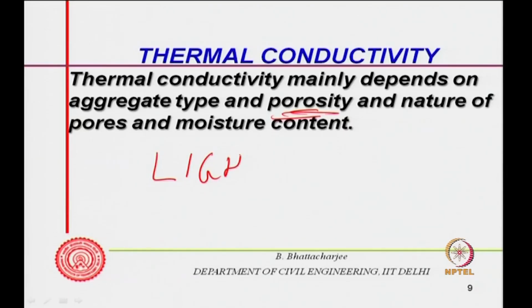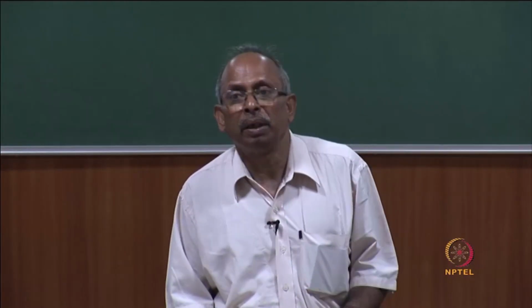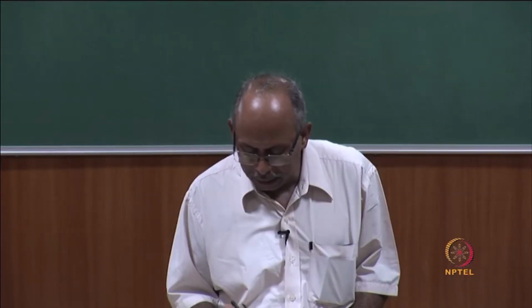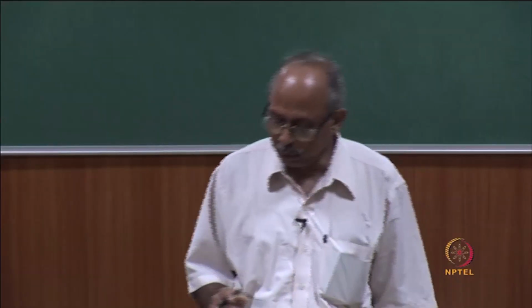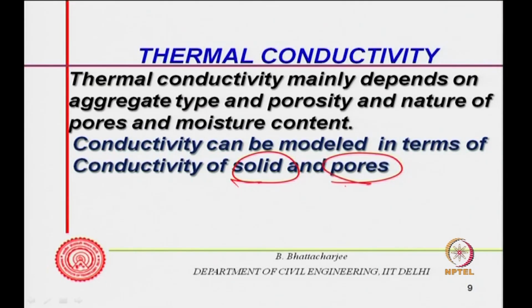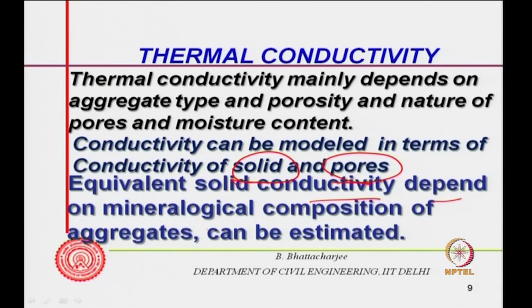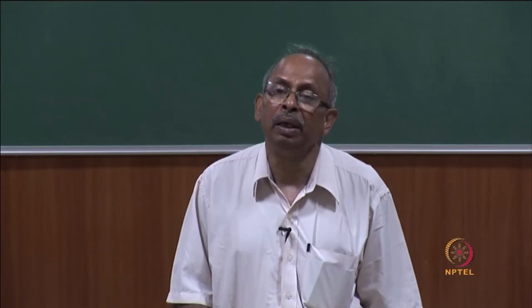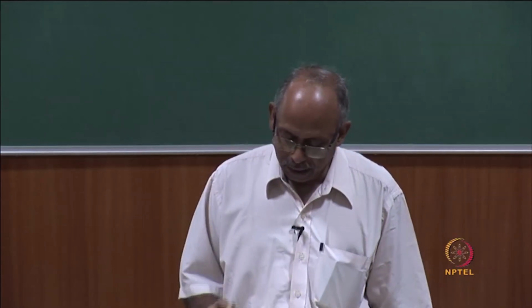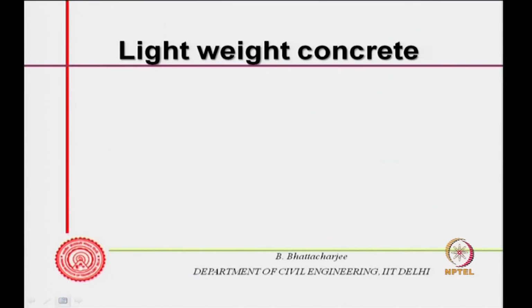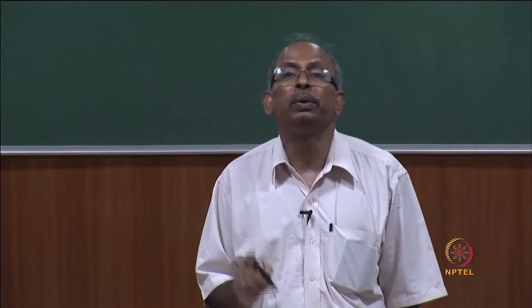How lightweight? Well, essentially high porosity means lightweight. Thermal conductivity depends on aggregate type of course and the porosity. Aggregate is the one which has its own conductivity, but the porosity governs it, and the nature of the pores also governs somewhat, but I am not interested in telling you about the nature of the pores. So, it depends upon the conductivity of the solid and the pores, and the solid conductivity will depend upon the mineralogical composition of the aggregate. For example, quartz or quartzite has very high thermal conductivity compared to other types of aggregate. So, lightweight concrete is basically because of porosity. Low porosity means high density, high porosity means low density.